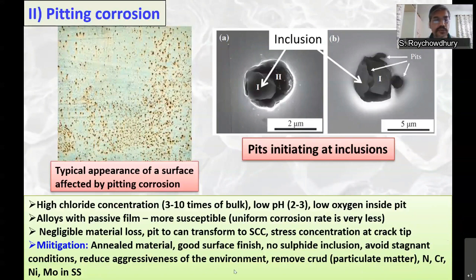Addition of nitrogen, chromium, nickel, and moly in stainless steels will again increase the resistance to pitting corrosion. Like moly-containing stainless steel: 304, if you add moly, it becomes 316, with around 2 to 3% moly, which increases resistance to pitting corrosion. If you add nitrogen, like 304 LN grades, low carbon nitrogen containing, there is high resistance to pitting. Also, an increase in chromium concentration and nickel concentration increases resistance to pitting corrosion.